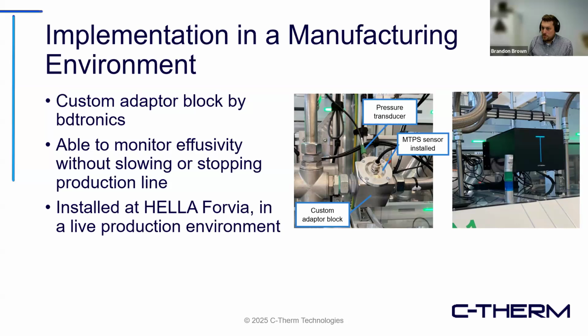The sensor was situated in a pipe where all the material processed from the bucket would pass through. During some of the initial testing after installation, we checked again and we were able to successfully measure the material's effusivity without slowing down or requiring a stop of the pump, at established pump speeds required on this production line, which was super important because we weren't allowed to stop production. That said, the material flow rate was relatively low. I believe it was something like a small number of grams per minute. Next slide, please.